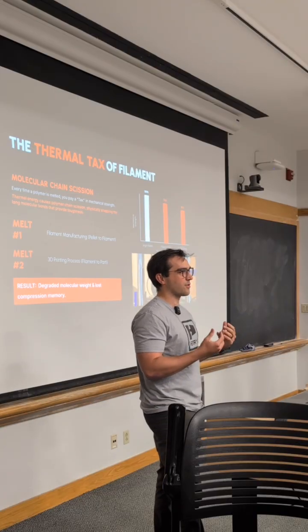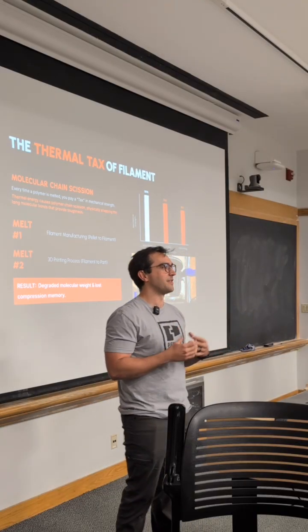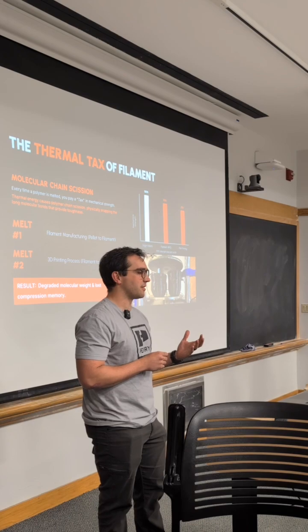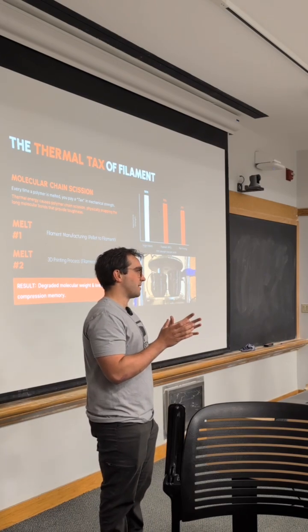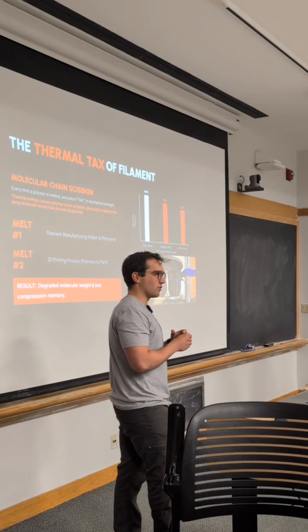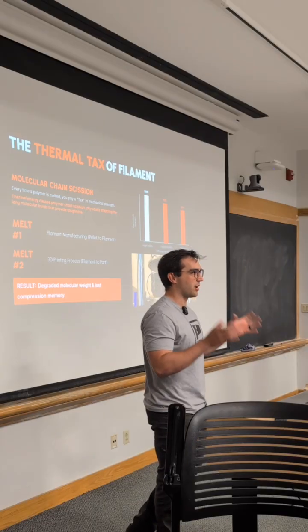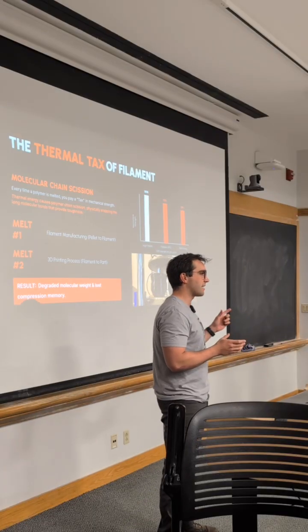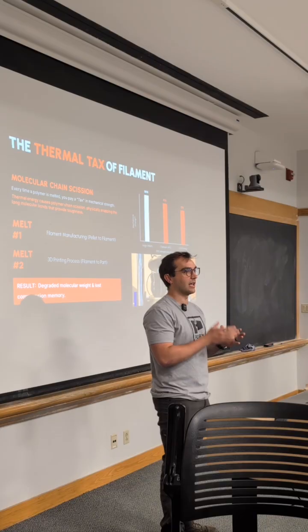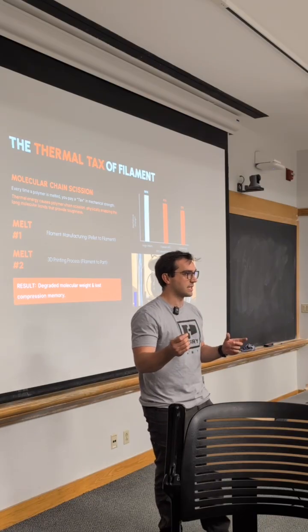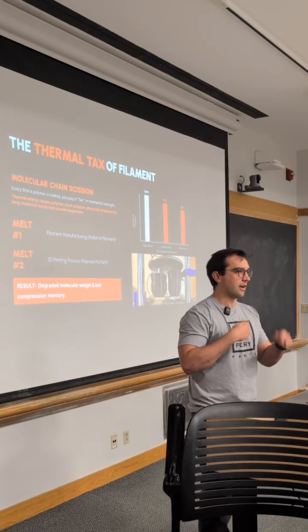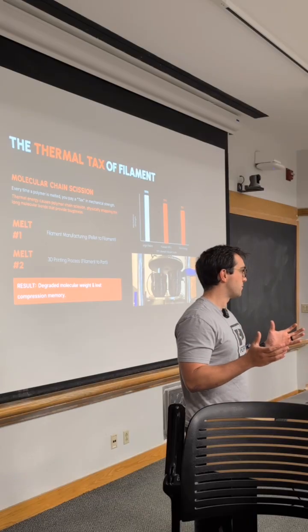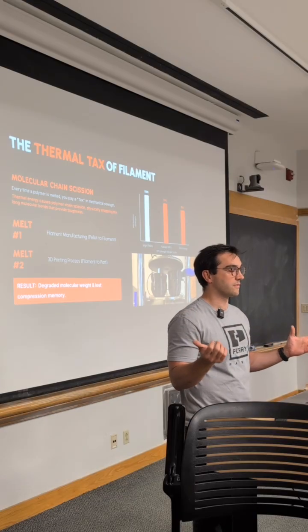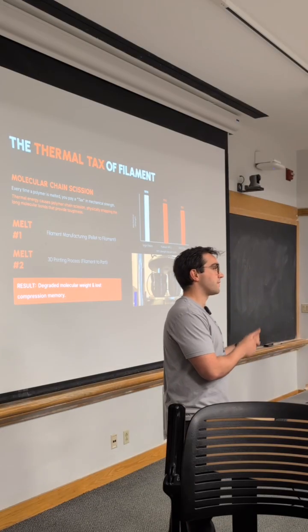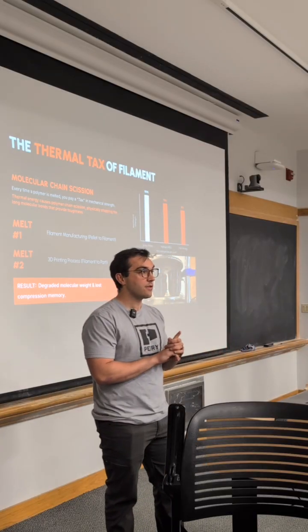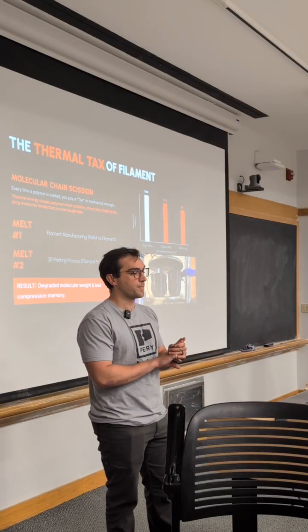And that kind of brings us to one of the core fundamental limitations of 3D printing filament. 3D printing filament, by its very nature, you're already printing a recycled polymer. Because in order to make filament, you have to melt the polymer at least once. Put it through the die, pull it, run it onto a spool, and then that's already been melted once before you even put it in your printer in the first place. So by the time you've made a finished part, you've melted the material at least twice, often 3 times.